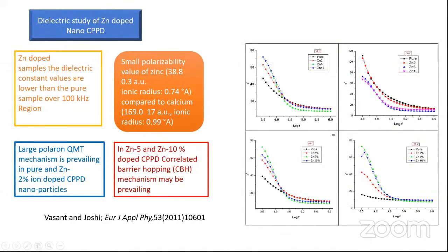Now, the dielectric study of zinc doped nano CPPD. The dielectric constant values of zinc doped samples are lower than the pure sample over the 100 kilohertz range. The small polarizability value of zinc and less ionic radius may be responsible for the lowering of the dielectric constant. From Jonscher's power law, one could predict that the large polaron quantum mechanical tunneling mechanism is prevalent in pure and zinc 2% CPPD nanoparticles. But in the other two concentrations, zinc 5% and zinc 10% doped CPPD, the correlated barrier hopping (CBH) mechanism prevails for conduction. Again, the results are published in our earlier papers in 2011.